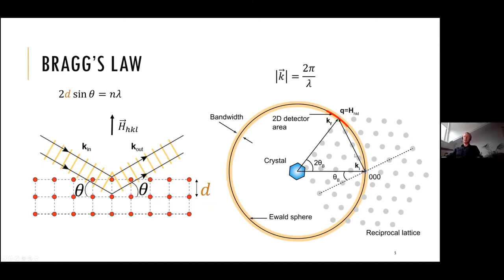Taking the difference between Kf and Ki, we can construct the Q vector, or the Q space of wave transfer vectors. By choosing a certain orientation, the end of this Q vector aligns with the position of the H vector for the certain crystal or reciprocal lattice. In this case, we can record the Bragg reflection. The bandwidth is basically shown by the thickness of the Ewald sphere. So the bandwidth of your radiation gives some width, and you record some area around the Bragg peak on your detector. So this is the basics of how we are going to treat the diffraction.